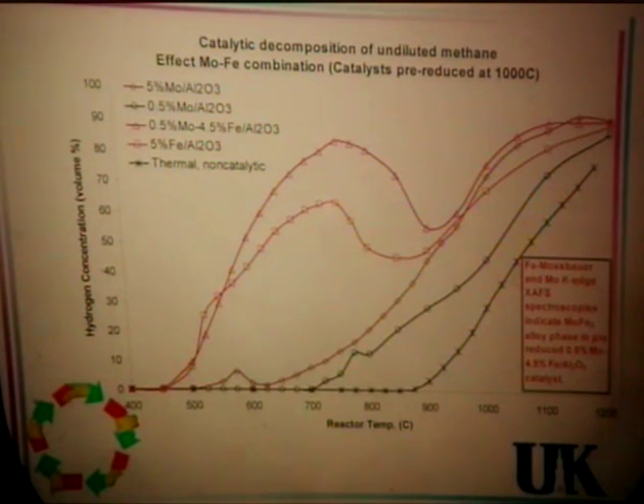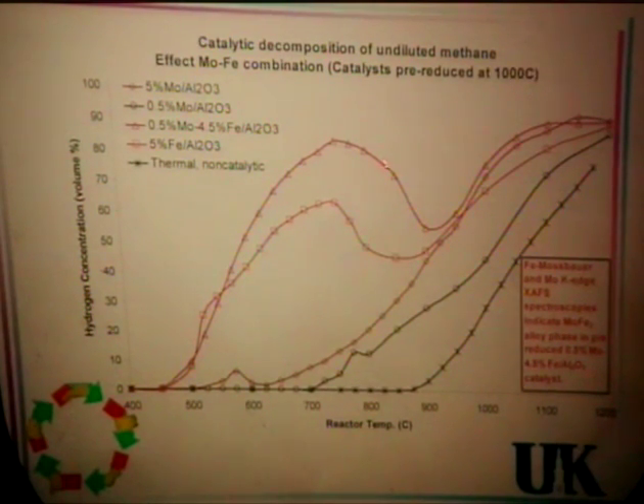Coming to the binary metal, 0.5% moly and 4.5% iron on alumina shows better activity at lower temperatures compared to the thermal cracking. The Mössbauer spectroscopy indicates that the iron moly catalyst has an alloy in the pre-reduced iron moly catalyst.